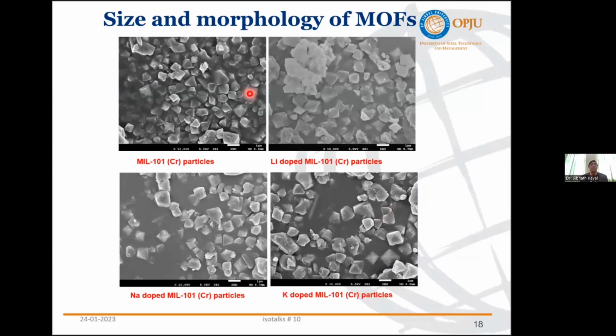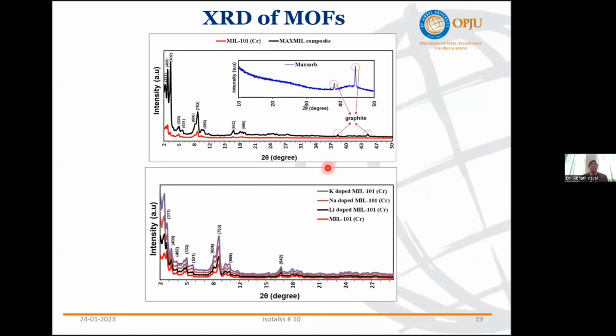This analysis we use to identify what is present in the synthesis. We have found the corresponding standard peaks of MIL-101 chromium, their corresponding lattice planes, and interestingly, after doping, we observe that there is no change or shift in the peak positions in the XRD. The MOF structure, MIL-101 chromium, has a cubic structure. That cubic structure is not disturbed by the doping.